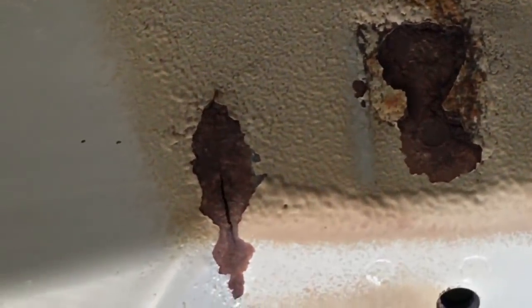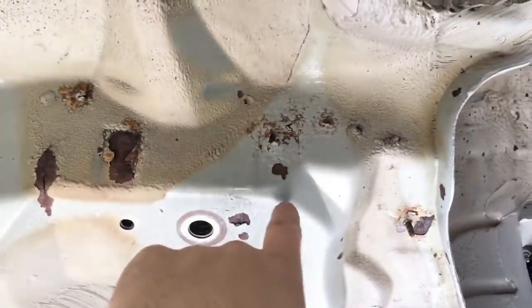This side, the left rear, we've got the typical crack here, which actually opened up. There's quite a gap in that one now, and it's corroded, plus spot welds, a couple of spot welds broken there. You can see the crack or the split in the seam sealer where the panel is separated from the wheel arch panel very slightly.